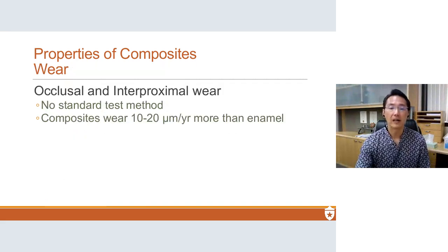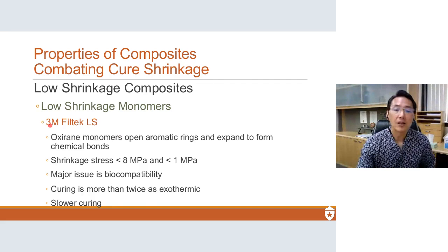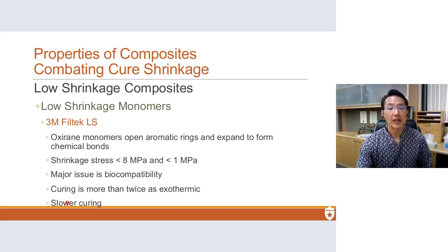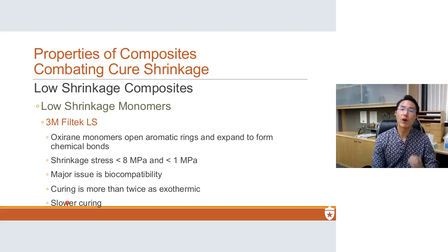Now, the major issue is still biocompatibility with the curing system. Epoxies are much more exothermic during their cure than methacrylates. Methacrylates get hot enough, but epoxies cure much more exothermically, so that's a concern. And they cure more slowly, which actually allows them to relieve the curing stress, but traditionally epoxies have been very difficult to light cure, okay? This product is actually no longer on the market. From my understanding, talking to people from their company, one, it's much more expensive. It's also sticky. A lot of clinicians I've spoken with say that it's very sticky and not easy to manipulate. So it seems that those two factors spell its demise.